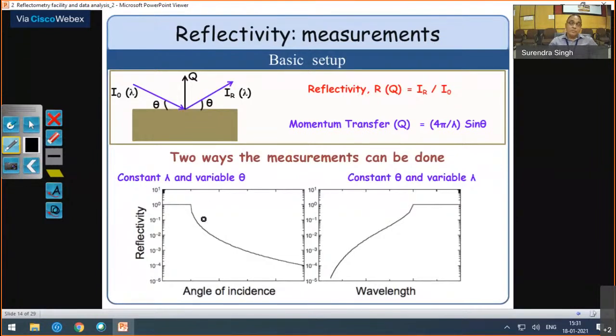If we change the angle of incidence at a fixed lambda, that gives reflectivity as a function of theta. And if you change both lambda and theta in Q, then you get reflectivity as a function of Q.